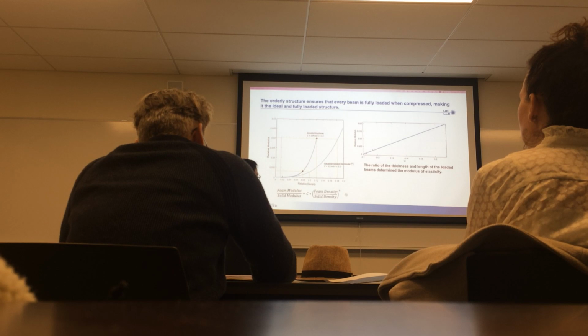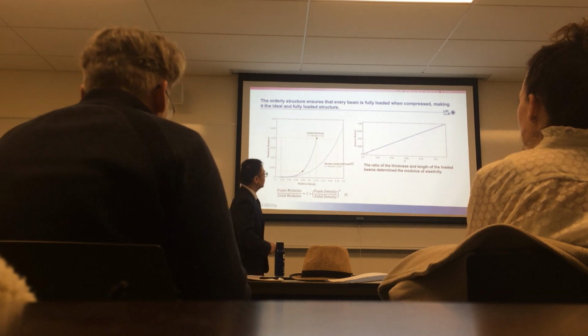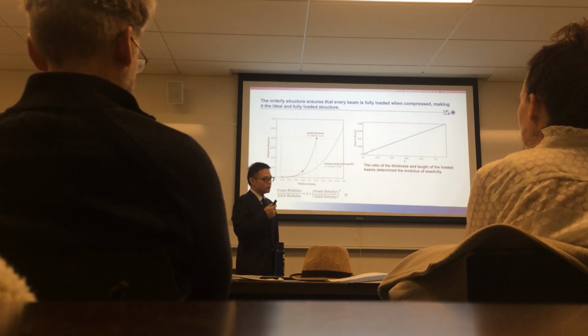They have higher values than the traditional random structures. That's because I think our auxetic structure is an orderly structure. So every beam is fully loaded when compressed, which means the material density is loaded with stress during the compression. Because of this, I think the relative modulus should have some relationship with the thickness and length. So I got the plot, and I found that there is a linear relationship between these two values. Which means in the future, when we want to design these orderly structures, we just change the thickness and the length of the loaded beams.